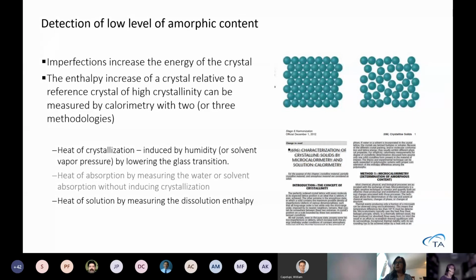So we can measure this calorimetrically, either by the heat of crystallization. We can induce crystallization by humidity, so we lower the glass transition and induce a crystallization of small amounts of amorphous content in our formulation. It's possible, I put this in a little gray here, that we can measure heat of absorption by measuring water or solvent absorption without inducing crystallization, because there will be different absorption behaviors. I will not talk about that today, but that's a method we see more and more used. And then we can do it by heat of solution, measuring the enthalpy of when I dissolve the substance. These two methods, I will briefly talk about them. There is a USP method that describes both these methods, also how to quantify or detect this.